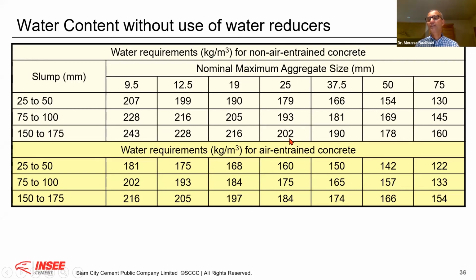if the maximum size of aggregate is 25. That is why very often in ready-mix operation we use super plasticizer. Therefore, we can cut by almost 20% the amount of water we add. It's okay. Therefore, you see, depending on the class of consistency, and depending on the maximum size of aggregate, you have different amount of water you can use for non-air entrainment and with air entrainment. When you entrain air, because air has the ball bearing effect, you see, here I use 202 liters, here I use only 184, almost 20% less.